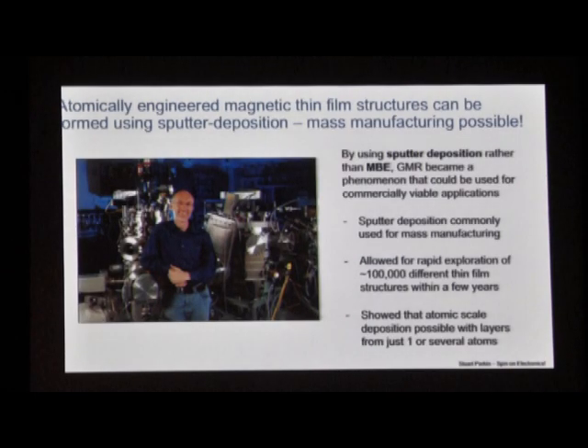So it turns out that in the early days of GMR, the phenomenon was poorly understood, and the effect was believed to be related to this whole concept of spin-dependent scattering within the bulk of the magnetic layers. But it turns out that, as I showed, this effect really is derived from scattering at the interfaces between the magnetic and non-magnetic layers. This is extremely important in order to understand the physics, but it turns out to be very important technologically, because this means one could use very thin magnetic layers to achieve large changes in resistance. And this is very, very important to create sensitive field sensing devices that can detect tiny magnetic bits.